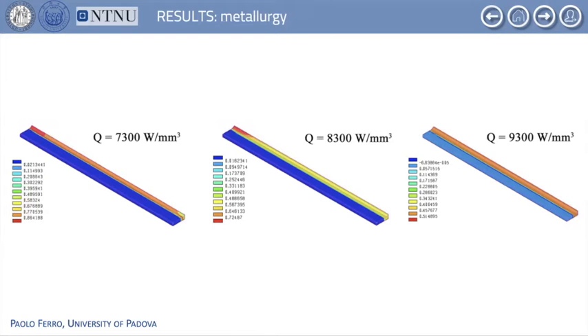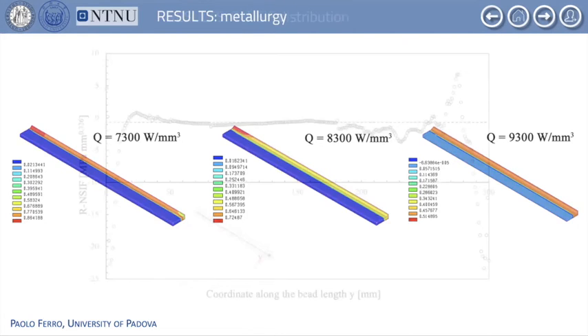Regarding the S355 steel microstructure, it is observed in the present figure that the weld bead is characterized by a mixture of bainite and ferrite, with an increase of ferrite as the power input increases. This is due to a decrease of the cooling rate with the increase of power input. Moreover, a stationary distribution of the microstructure is observed along the central part of the joint.